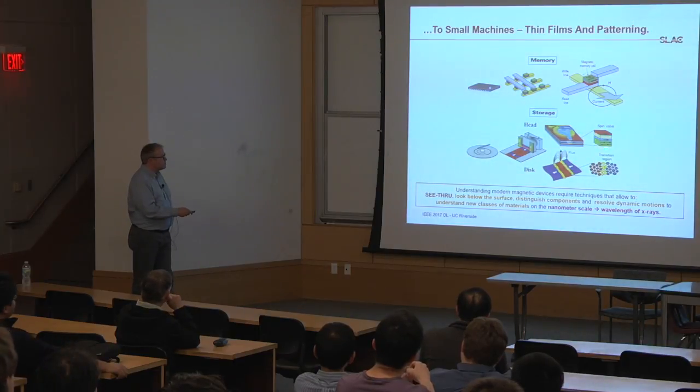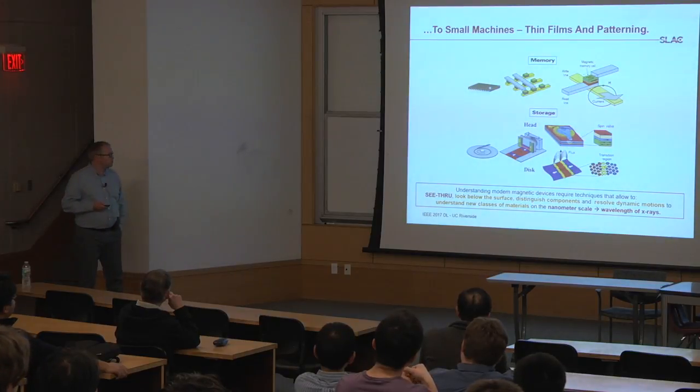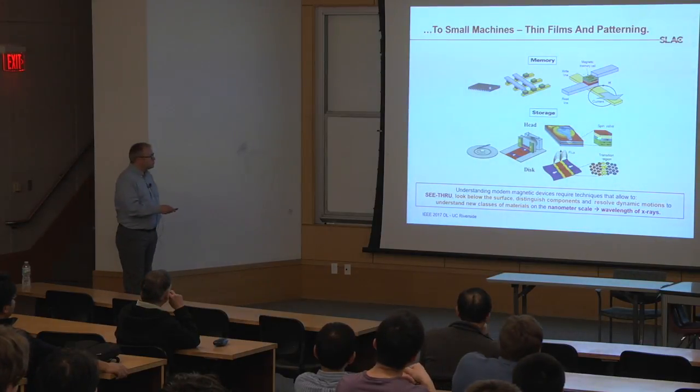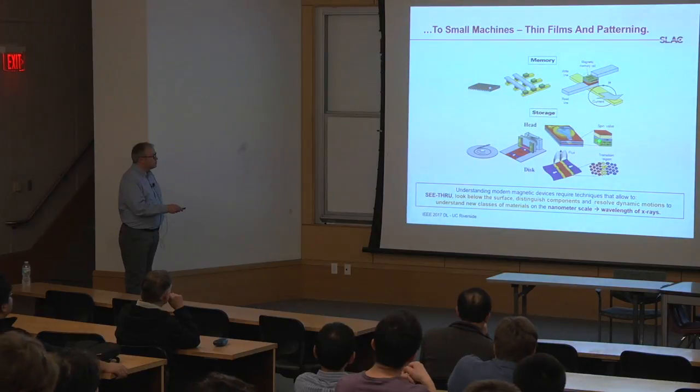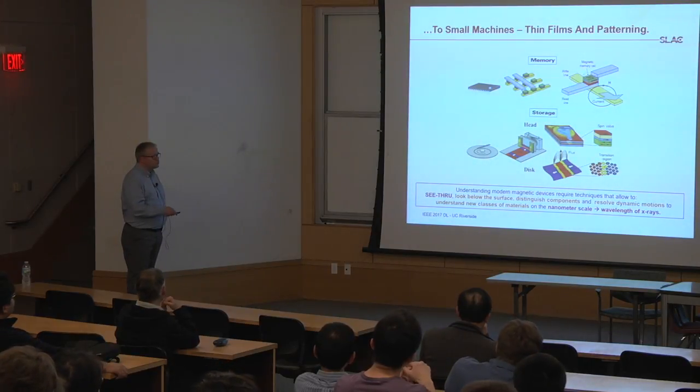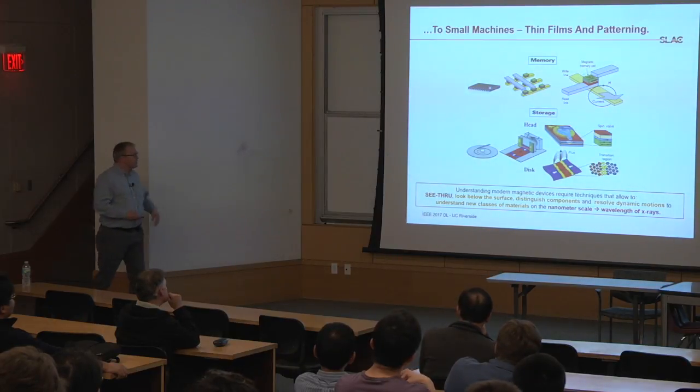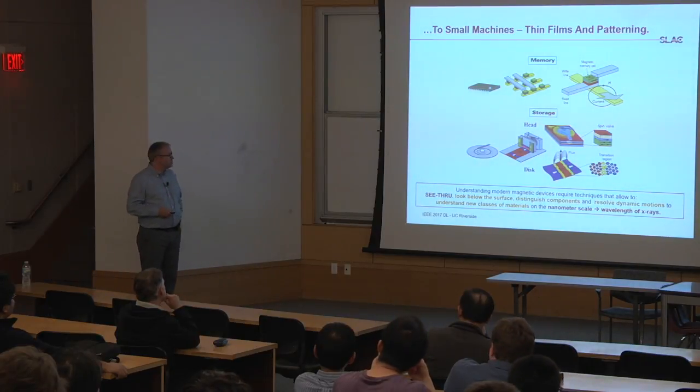So this interface here, the antiferromagnetic interface, is something that I worked on quite a bit during my PhD thesis. Essentially what you achieve by doing this is that you keep the ferromagnetic layer fixed in one direction as a reference layer. Now you have a very sensitive sensor that actually allows you to read out the information on a hard drive that comes from smaller and smaller bits.